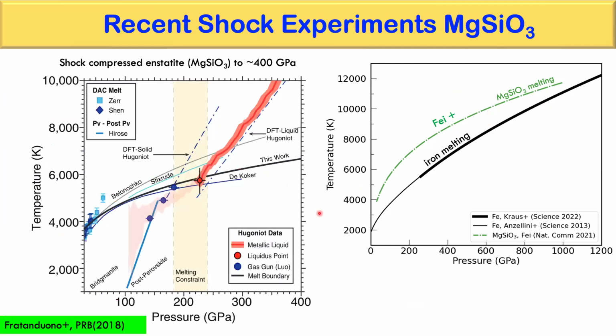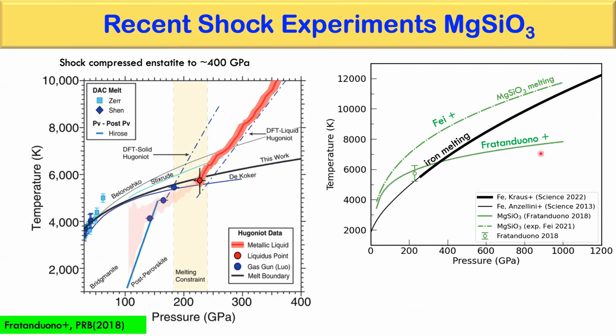But there are other experiments that have been performed at these extreme conditions that started with exactly the same material, but with a different phase of the material, and placed a constraint over here at lower pressures. And according to this experiment, this is the melting line that they obtained, which is considerably lower. And it has really important implications for planetary evolution, because if you have a melting line of silicates below the melting line of iron, that will mean that the core starts crystallizing before the mantle does, which is completely reversed from what happens for the Earth. And whether that actually happens depends on whether we can confirm these experiments.